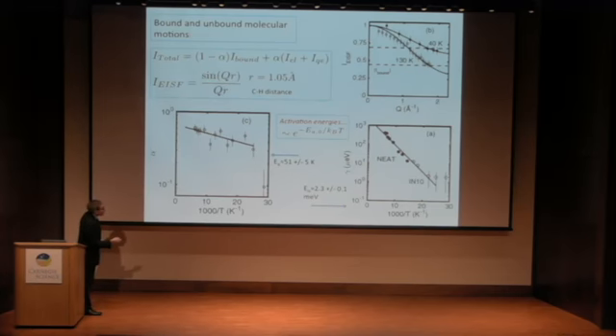We can also plot the energy width as a function of temperature, from which we come up with, I think, a fairly surprisingly low energy scale associated with this rotation. It's about 2.3 milli-eV, or about 25 Kelvin. Okay, so that's the story behind the molecular rotation.